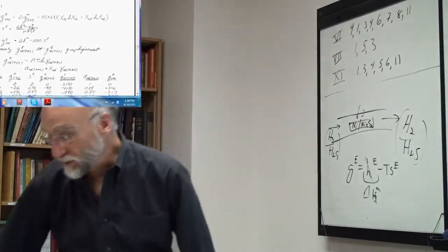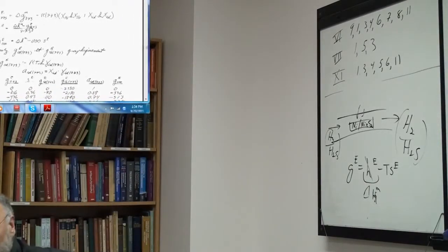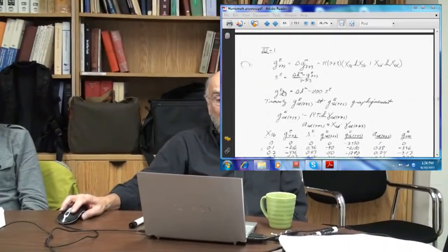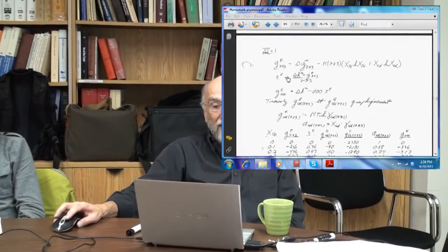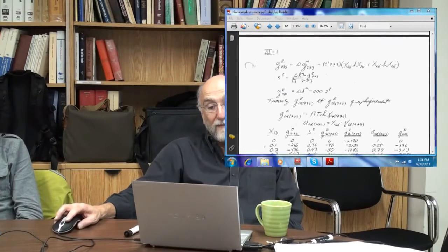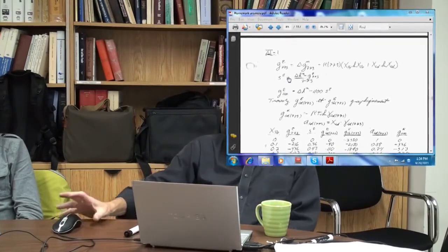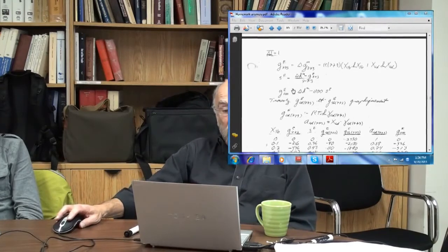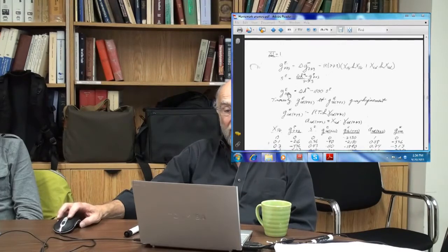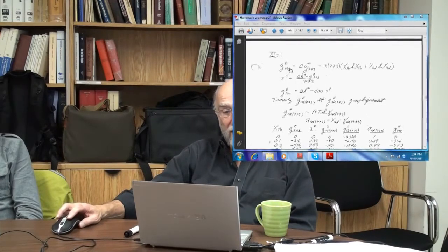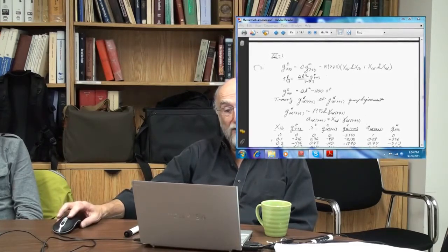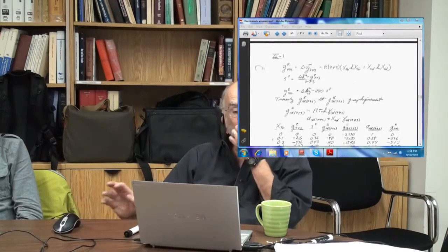The temperature is 773. At 773, which is the temperature of measurement, I can calculate the excess entropy. So now I have the heat of mixing and the excess entropy, which I'm assuming are temperature independent. Now I can use the equation Gxs equals delta H minus T Sxs to calculate Gxs at any other temperature. The measurements were at 773. I measured G and H, so I get S. If I assume that S is independent of temperature, then H is too.